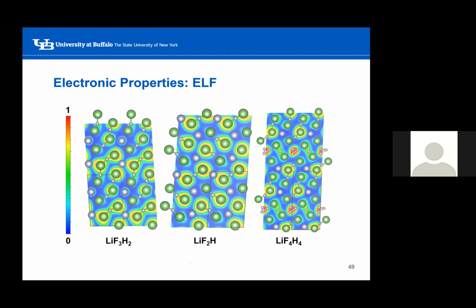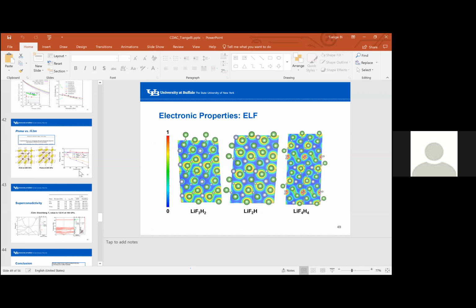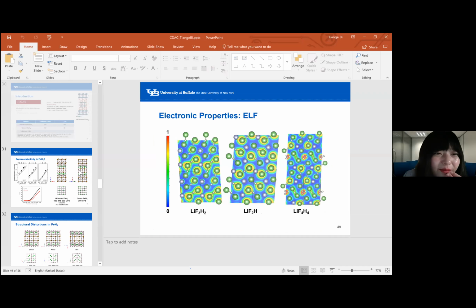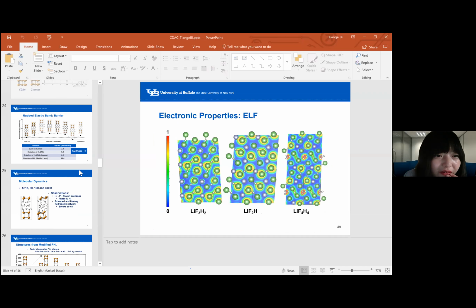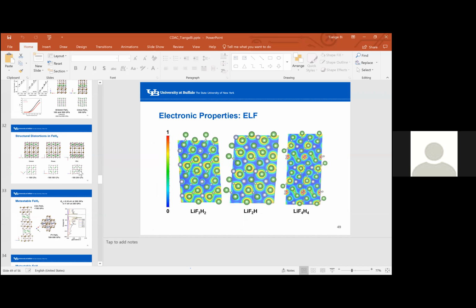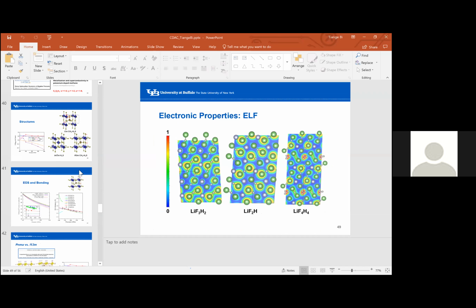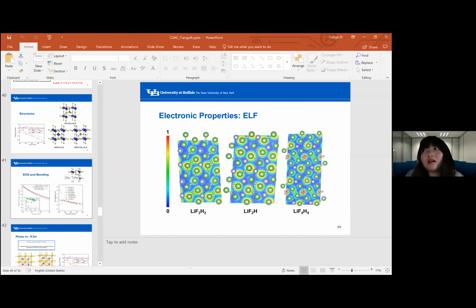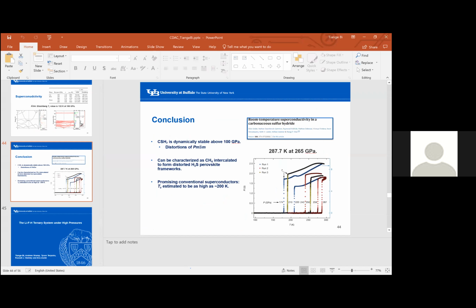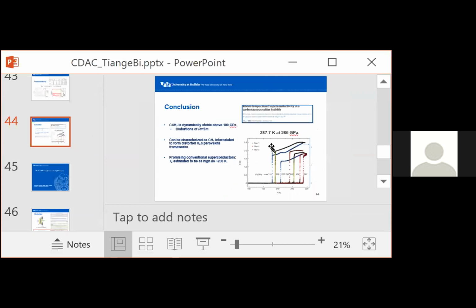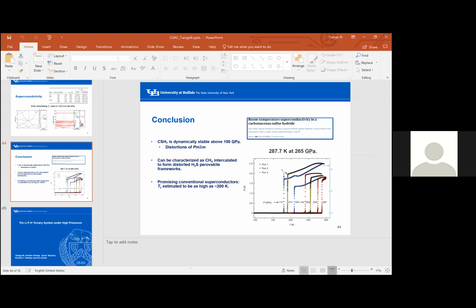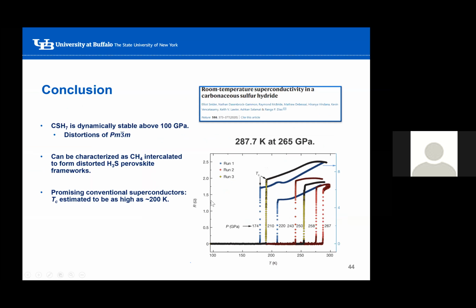Lower TC than what was observed experimentally in the Dias experiments. Yes, comparing to the trihydrogen sulfide, it would have a lower TC. Not only compared to the trihydrogen sulfide, but compared to whatever Dias and co-workers found. Yeah, the TC is lower. So you haven't explained the Dias et al. results, that maybe there is some other carbon-containing structure. And I know of some preliminary work on just doping carbon instead of sulfur, but your calculations with methane do not explain the high TC.